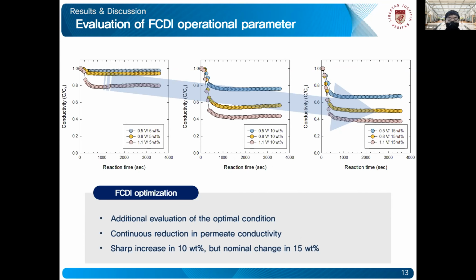Now, applying the optimal condition previously found, we ran the operation of the FCDI again through a feed concentration of around 5,000 brackish water concentration. As predicted, increase in the applied voltage and mass loading led to the continuous reduction in permeate conductivity, as can be seen. However, with nominal changes between the 10 and 15%, the optimal condition was confirmed.